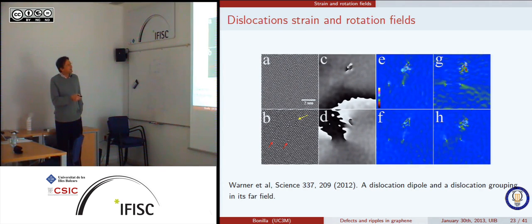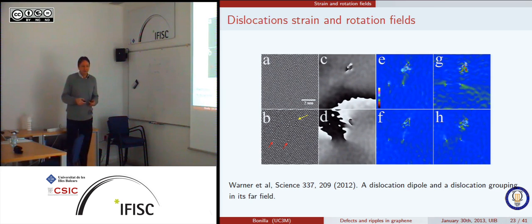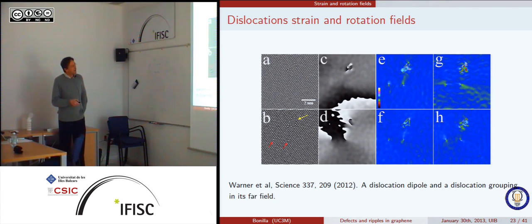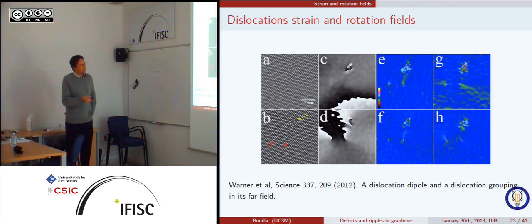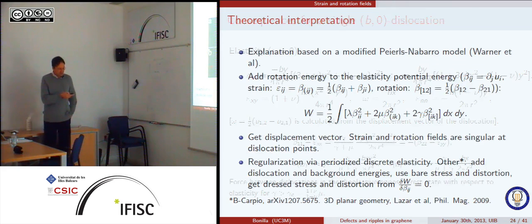Sorry. So these are a group of defects, and then there is a dipole here. So this is just 5-7 defects, one directed to the, say, to the left, the other to the right. Now, we took the defect that is farthest from this piece of defects and some junk that there is there, and calculated from the experimental data the strain and the rotation field.